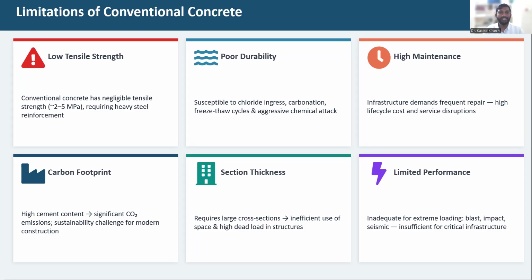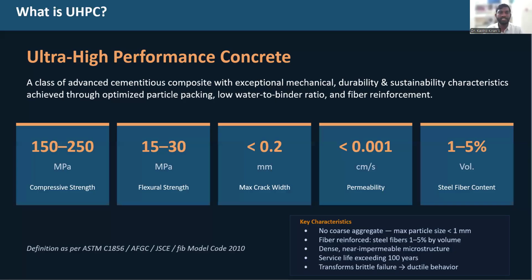So considering all these limitations of conventional concrete, we have a better one, which is ultra high performance concrete. In simple terms, ultra high performance concrete gives a strength between 150 to 250 megapascals. Again, this is not a standard value; it's a typical value reported across the literature which I have studied. It also yields up to 15 to 30 megapascals of flexural strength, which is a very good sign for utilizing it in bridge decks, girders, or large scale construction. We can also minimize the crack width to less than 0.2 mm, which is better than any other type of concrete available in the industry at the moment.